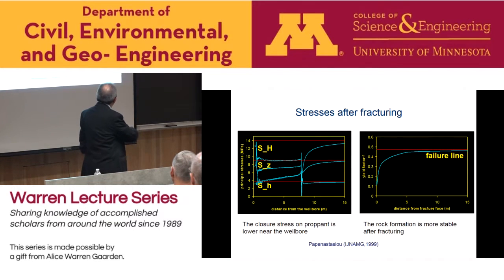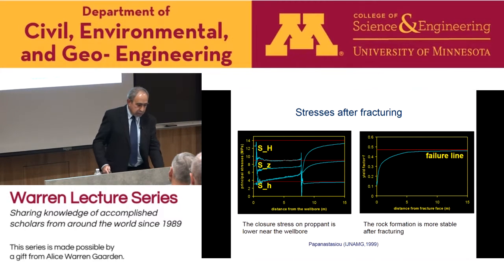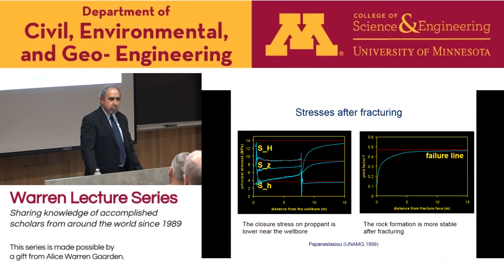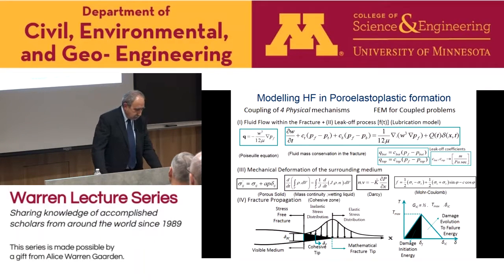And the other thing we found is that after the fracture has closed on the proppant, it's much more stable to deformation. Before fracturing, you can see actually in this diagram here, which I call the yield factor, the fracture is here, and this is a line perpendicular to the fracture face, okay? If you go far away, it's like not having any fracture. And here we selected the parameters to be very close to the yielding. After we did the fracturing and we look at this yield factor, we found that we push it away from the failure line. So the formation is more stable, and it will not fail to produce sand for the frac packs applications which I mentioned.